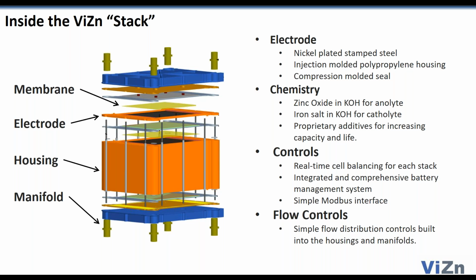The chemistry that we run through the stack is a zinc oxide and a potassium hydroxide for our anolyte, and an iron salt and potassium hydroxide for the catholyte. If the two are mixed, you do lose some performance, but there's no catastrophic reaction or event that occurs from mixing. We can cross-contaminate to relatively high levels with negligible impact on performance. We have proprietary additives in the chemistry that really get us our capacity and our life in the product.